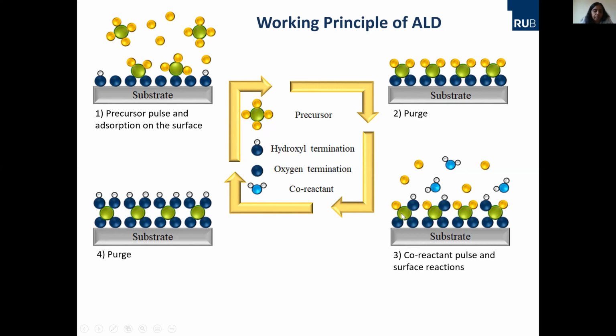And in this way, the excess precursor again is purged out, and you have a monolayer of hafnium oxide formed. So in the last step here, you see hafnium oxide formed, and this you can repeat cycle by cycle. You can increase the number of cycles. In this way, you can control the thickness.